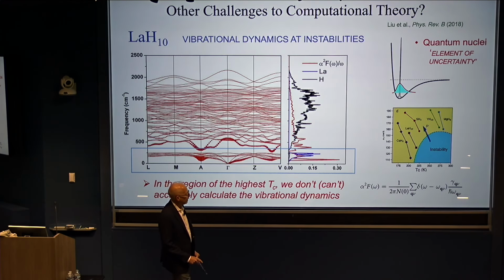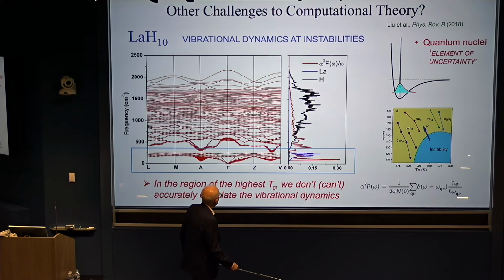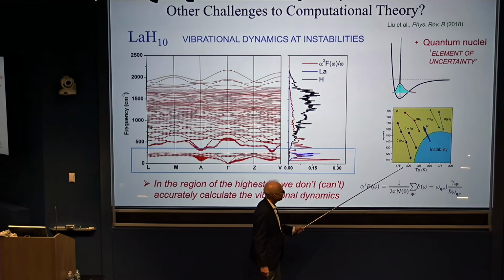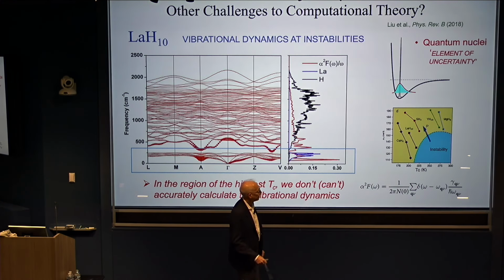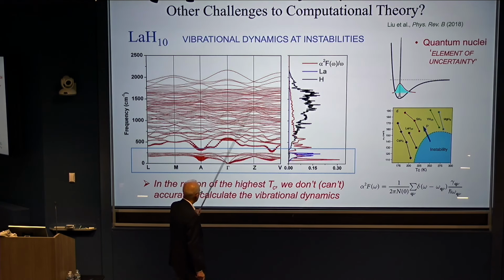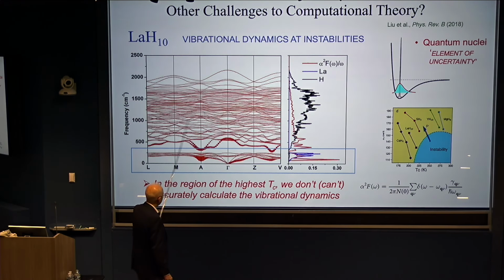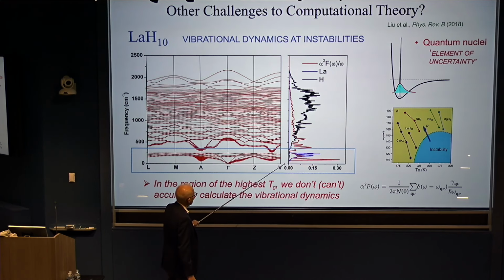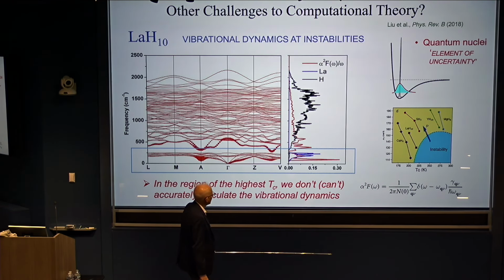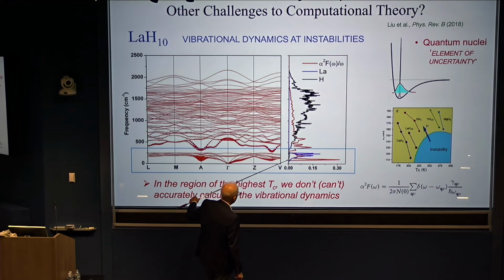The second problem, and I'd say as a challenge to theory, has to do with the problem of being near instabilities, and that also is connected to this very large zero-point motion effect. This is a complicated diagram, but basically it shows the vibrational frequencies of the system, and also these are bands that show how much a particular vibration is coupled to the electronic subsystem, so the electron-phonon coupling. And what we find in all of these systems when we do these calculations, and this again was for lanthanum H10, is that you get the maximum superconducting temperature as these modes soften. They're very close to zero.